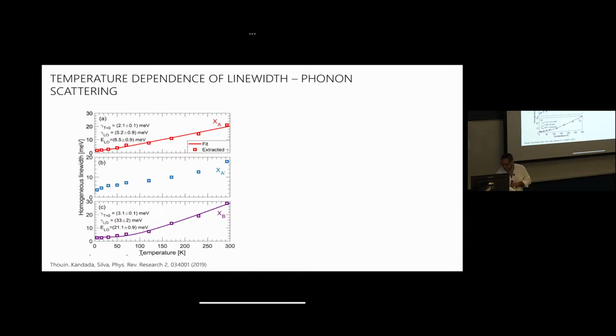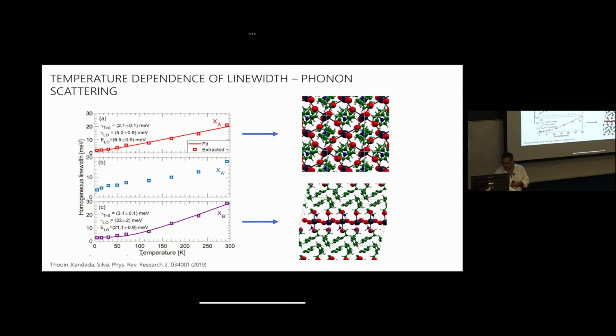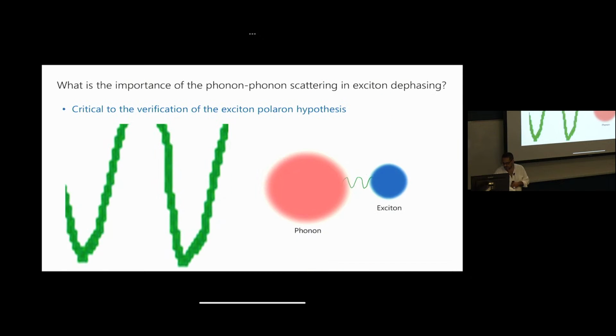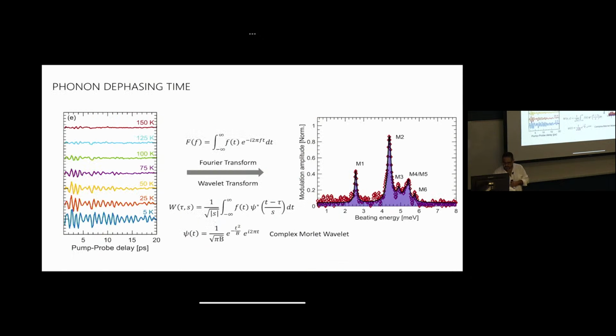And you can analyze that, and I'm not going to have time to get into Esteban's work, unfortunately, but let me just give you the gist of it, which is the question: why are certain phonons more important in dephasing than others? Why do certain phonons that couple differently to XA and XB more relevantly prevent or enhance exciton-exciton scattering? Why are certain phonons preferentially the ones that mix exciton A and exciton B to non-adiabatically relax from one exciton state to the other exciton state? And we need to understand the nature of the phonon-phonon interactions.